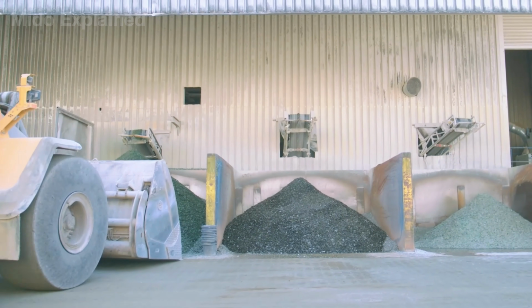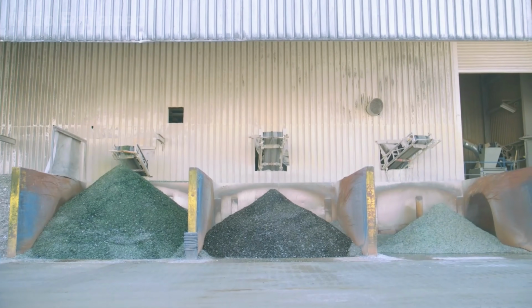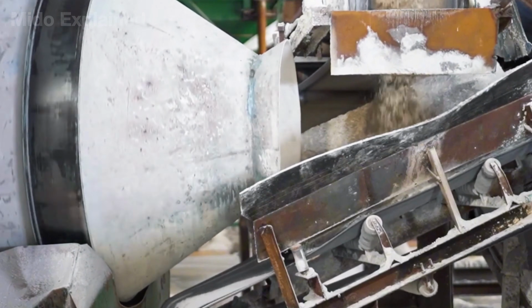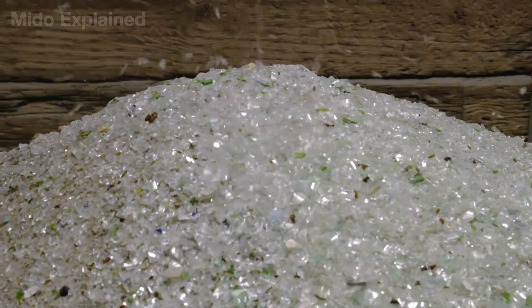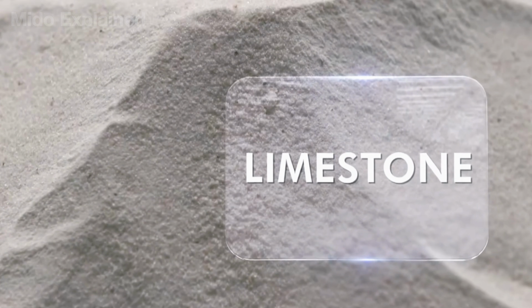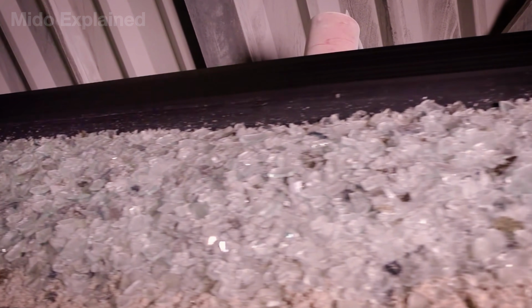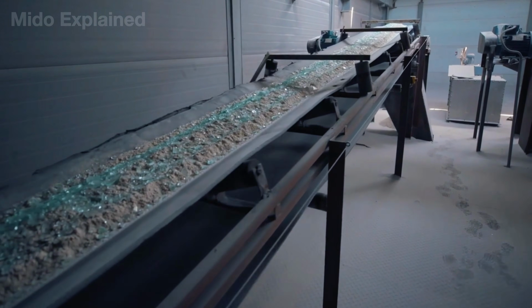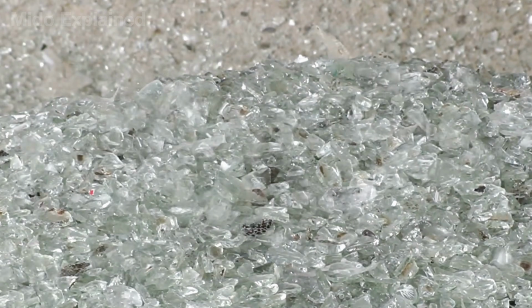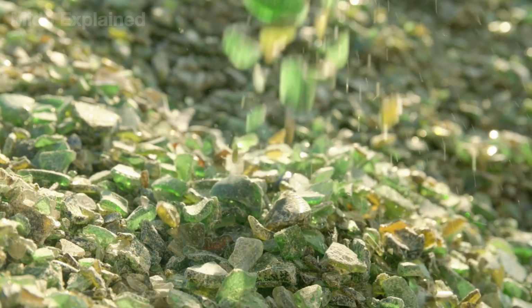At this stage, the color-sorted glass fragments are discharged into separate hoppers. From there, a dosing system automatically weighs each component with precision before feeding them into a high-capacity mixer. In addition to the recycled glass, small amounts of silica sand, soda ash, and limestone are added to adjust the chemical composition, ensuring the molten glass achieves the desired clarity, hardness, and durability. Depending on the quality of the input materials, the mixture may contain between 80% and 95% recycled glass. Tens of tons of material are continuously blended until all components are uniformly distributed.